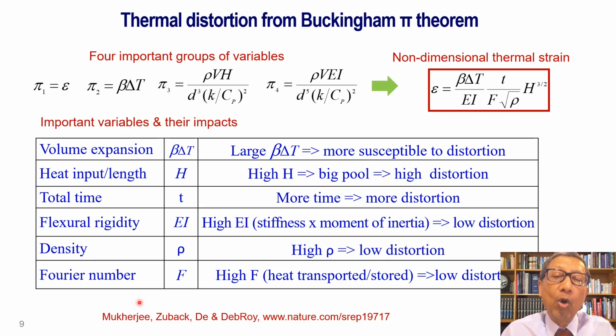So when we combine all of these variables into non-dimensional terms, we get 3 pi terms, and when we combine all of them, we get an expression for the distortion or strain, maximum strain, which is proportional to beta times delta T, which signifies volume expansion, and is proportional to heat input per unit length raised to the power 3 by 2. It's proportional to time, inversely proportional to EI, which represents rigidity, inversely proportional to F, which represents Fourier number, and inversely proportional to square root of density. So we are going to check how experimentally we can validate this expression.